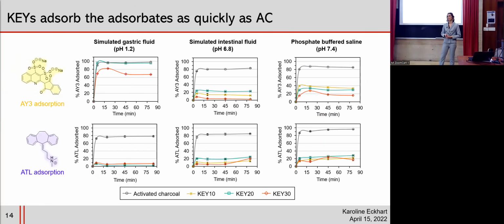So to answer that first question, we did a series of kinetic experiments looking at the % of each drug adsorbed over time. And from this data, we can see that the keys adsorb both the cationic and the anionic drugs as quickly as activated charcoal, if not faster. And that equilibrium is reached in about 15 minutes, definitely less than 20, but a little more than 5.